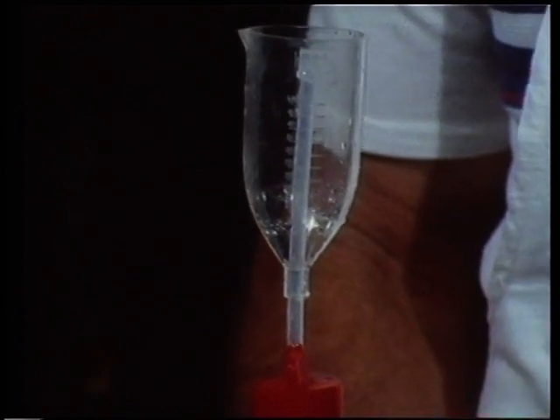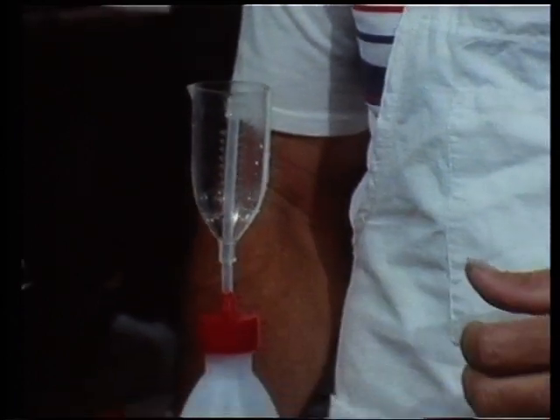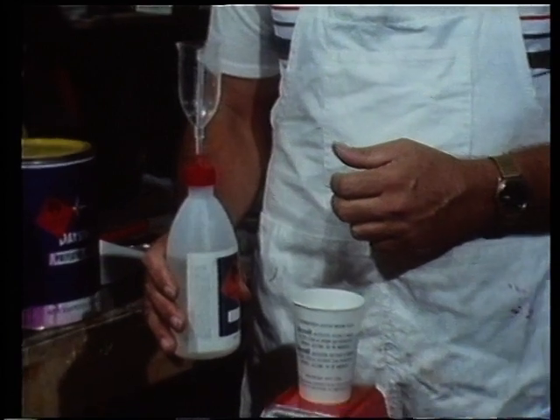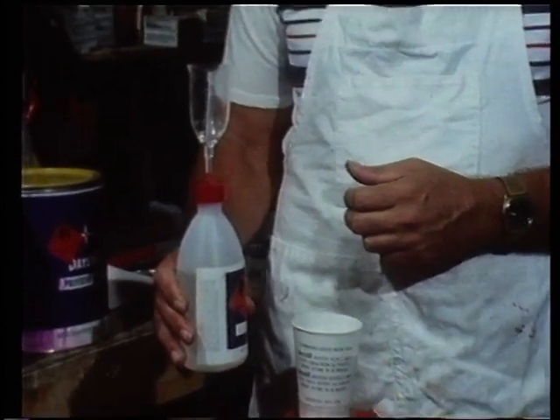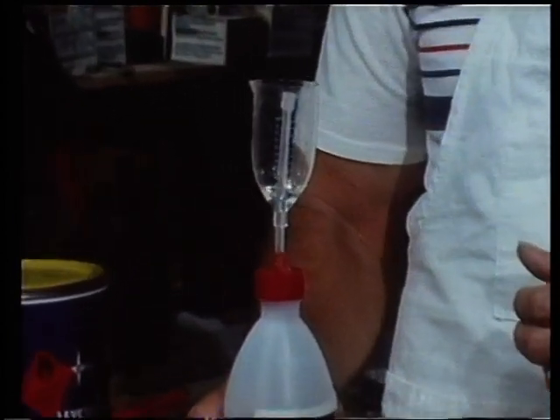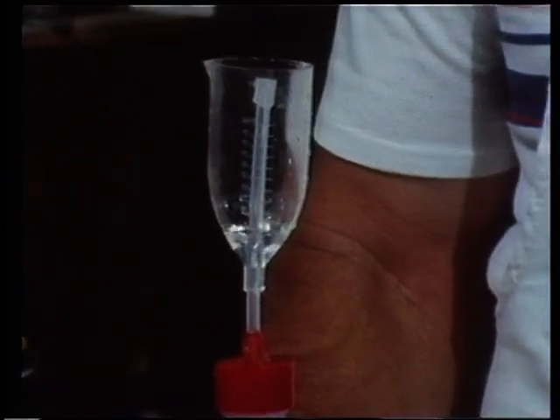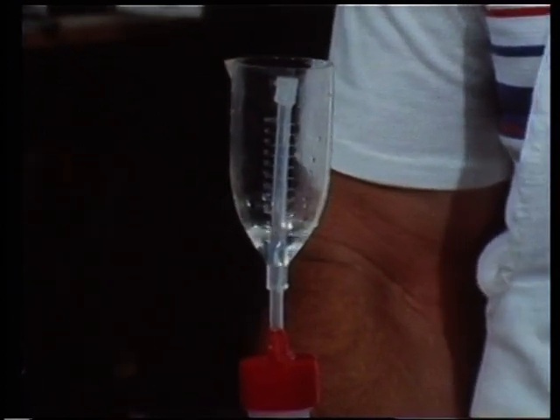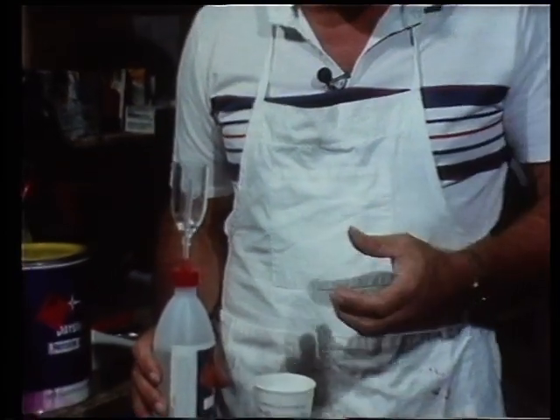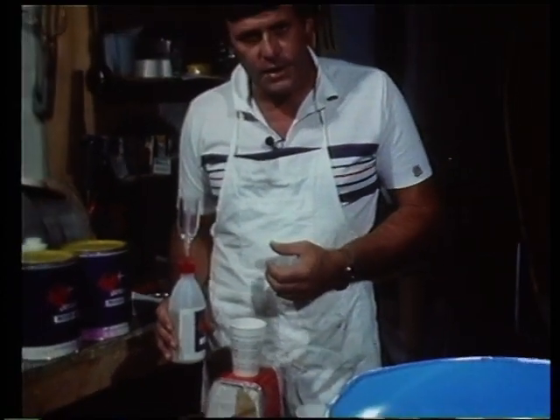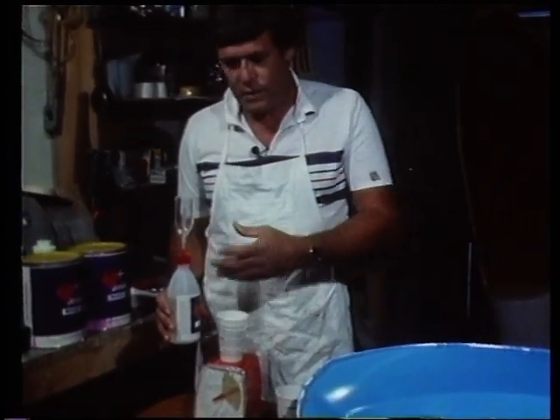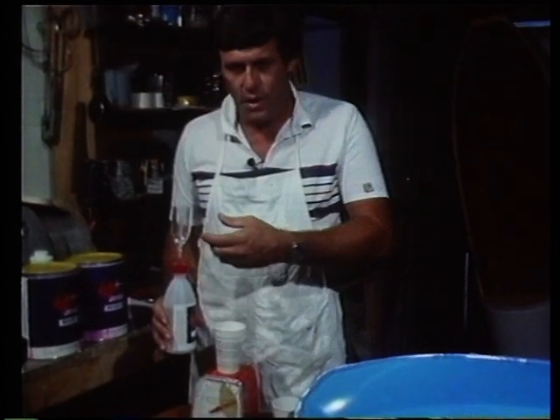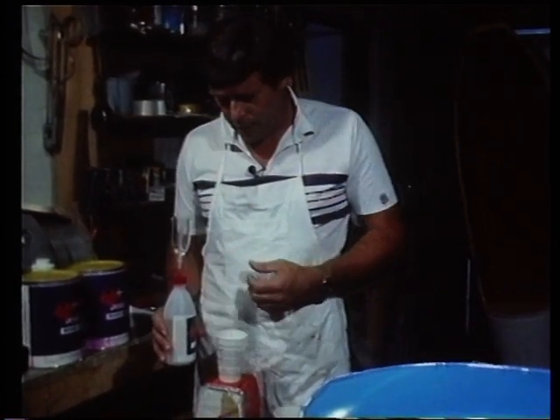Now this catalyst is in a special decanting bottle. What I do is squeeze the bottle, the catalyst moves up the tube, and if I stop just below the 5 mil graduation, I know that I have approximately 2.5 mils of catalyst. Now the nice thing about this material is that it's not critical in its proportions. Providing you have a minimum amount of catalyst in there, you will get a cure. So it doesn't matter whether I have 2 mils or 3 mils in there when I'm aiming for about 2.5.